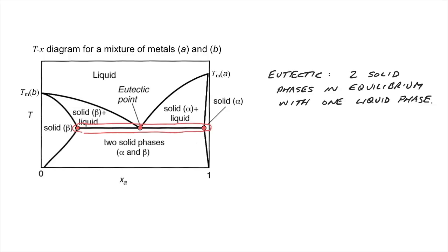You may have noticed the remarkable similarity of this diagram to the P-x-y diagram we examined previously. Indeed, a eutectic is exactly analogous to a heteroazeotrope. Just as the boiling point of a mixture is suppressed relative to the pure liquids near a heteroazeotrope, the melting point of a mixture is suppressed relative to the pure solids near a eutectic. Just as the relative volatility of the two species are opposite in the two gas-liquid regions above the heteroazeotrope, the relative solubility of A and B are opposite in the two liquid-solid regions above a eutectic.